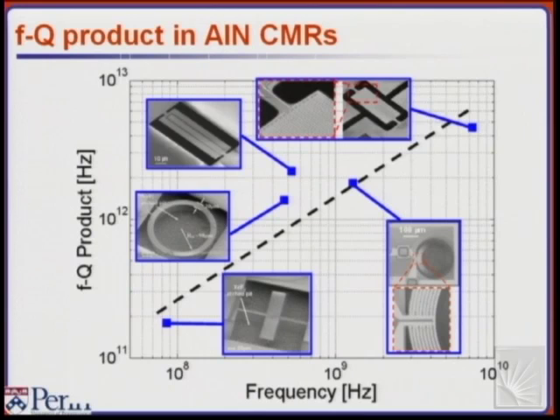We could harness at that point the advantage of making the device smaller for sensing application, as I'll show later, because we are improving the sensitivity of the device, but we're not reducing its minimum detectable frequency shift because the Q stays the same. So you can effectively improve the limit of detection of your device, for example. And you can explore basically doing similar solution with a high Q element even at high frequency.